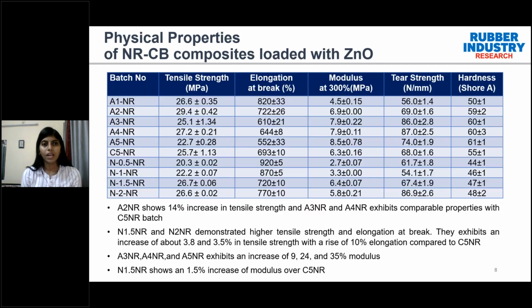And when we analyze the physical properties of the natural rubber composites loaded with the zinc oxide, such as tensile strength, elongation, modulus, tear strength, and hardness, we can see that the A2NR shows a 14% increase in the tensile strength, where A3NR and A4NR exhibit comparable properties with the C5NR, while N1.5 and N2NR demonstrate a higher tensile strength and elongation at break than the C5NR.